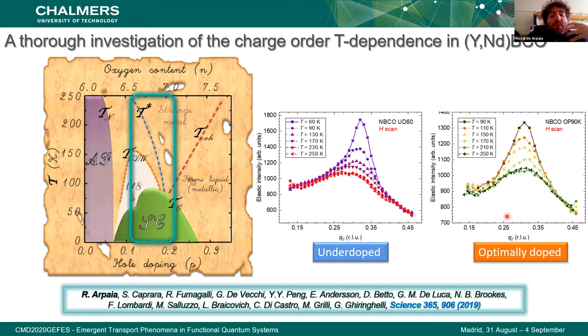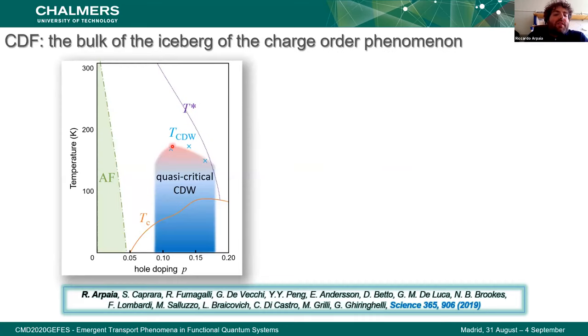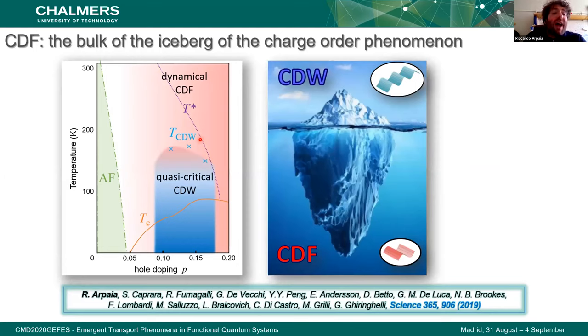So the situation is very much different from what was commonly believed till a couple of years ago, because this was basically the phase diagram that I showed you before, in which the charge density wave was just occupying a very small region of the phase diagram. But in reality, charge density wave is dominating the phase diagram of cuprates, since these charge density fluctuations, because they are short range, that are also dynamical because they are associated with finite energy, really occupy the whole superconducting part of the phase diagram. And so what we can see is that before, the charge density wave was just representing the tip of the iceberg of the total charge order phenomenon. And now we should expect that charge order, being pervasive, has to influence the properties of this material.